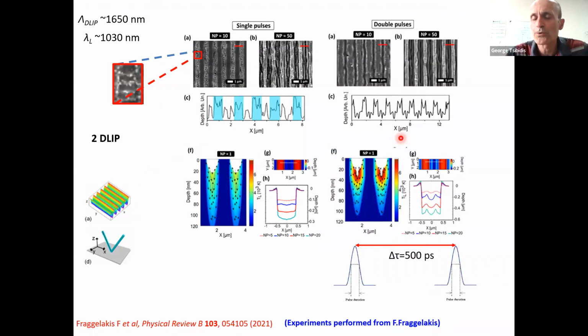And if we use double pulses, and when I say double pulses, I mean two Gaussian beams separated temporally by 500 picoseconds, you can see another deformation inside this crater. If you look at the profile produced after using a single pulse or two pulses, you see another crater. This is because the second pulse sees not the material in a solid phase, but after 500 picoseconds, a material in a molten phase. So the optical properties of the material which absorbs the energy are different, and so the energy which is absorbed is different.